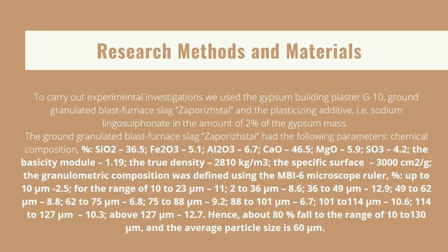Research method. To carry out our experimental investigation, we used the gypsum building plaster G10, ground granulated blast furnace slag Zaporizhstal, and the plasticizing additive sodium lignosulfonate in the amount of 2% of the gypsum mass. The ground granulated blast furnace slag Zaporizhstal had the following parameters that you can see in the picture.